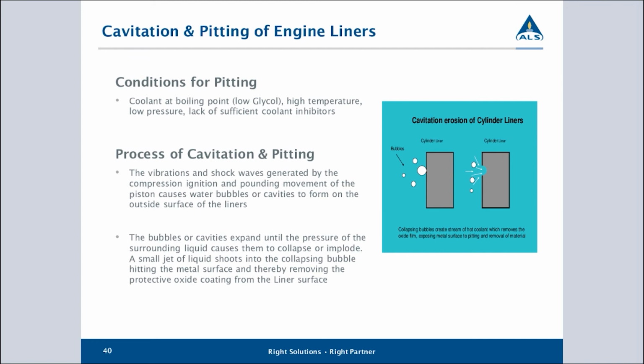Now, when this cavitation occurs, this bubble tends to break away barrier protection. So your organic acid style coolants are particularly susceptible to this issue, and you will tend to find a lot of pitting at the top end of the liner occurring because of this. And once we form a pit, you tend to have an area where the chemistry to form corrosion becomes ideal. And so we tend to form more corrosion inside the pit, and the pit steadily gets bigger and deeper and actually can start to channel into the surface.